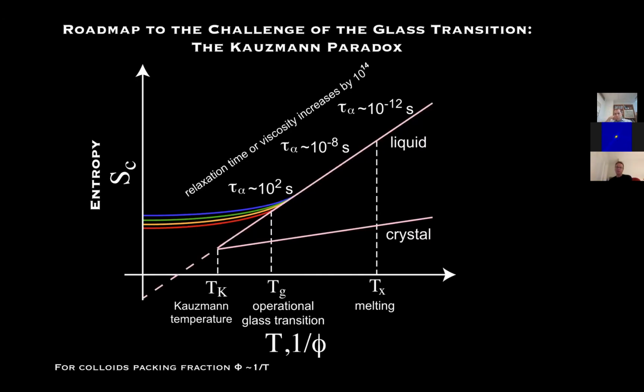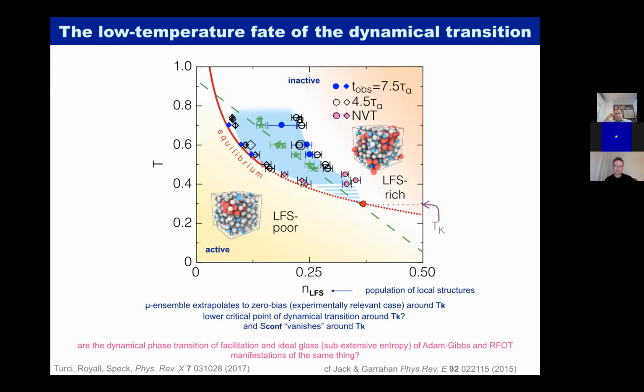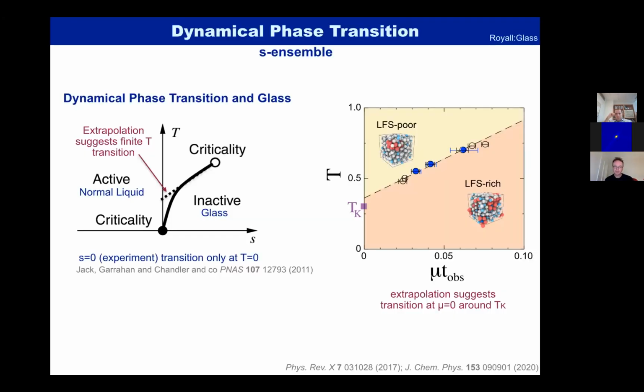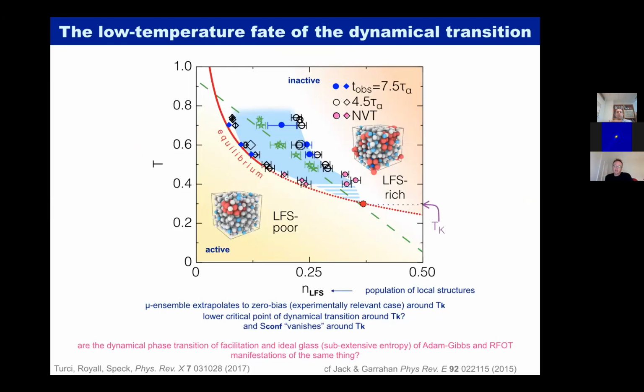So if I now come back to my original thermodynamic interpretation, it's starting to look quite curious, because this thermodynamic interpretation has a liquid and a crystal. I drop the temperature and they meet at the Kauzmann point. And what I'm showing here in a slightly different representation is that I have a dynamical phase and an inactive phase which meet at a temperature close to the Kauzmann point.